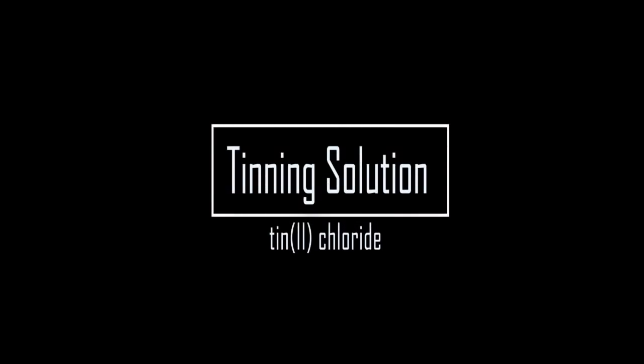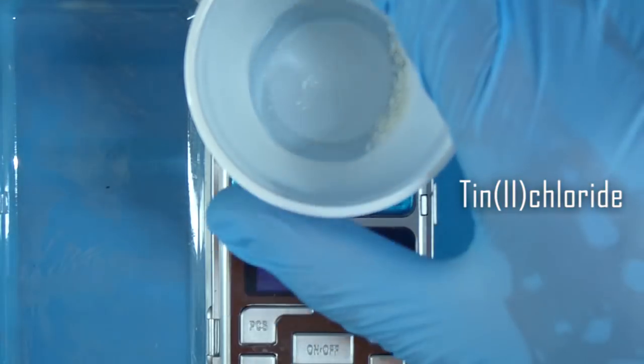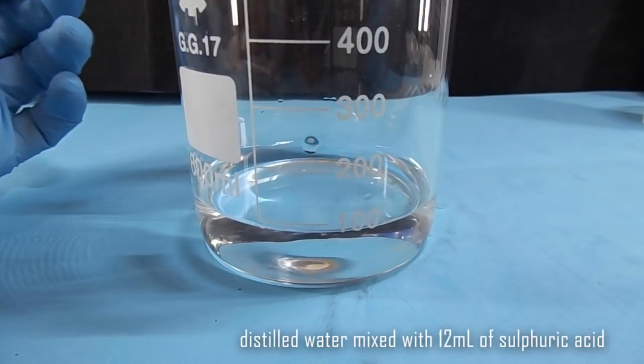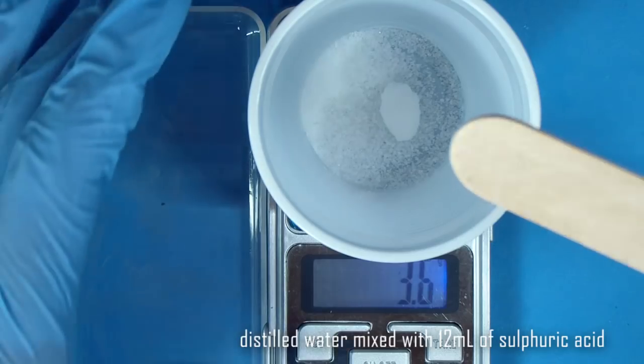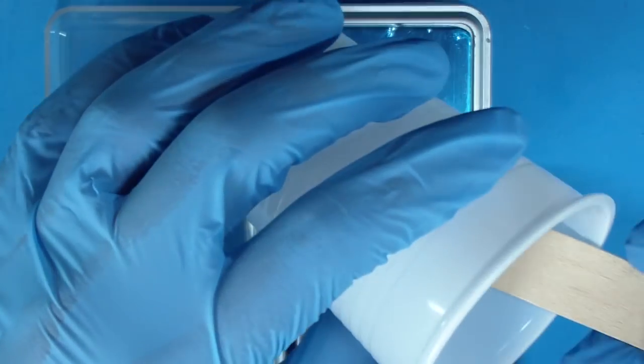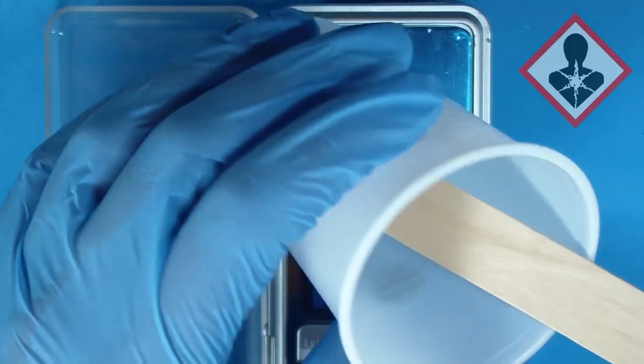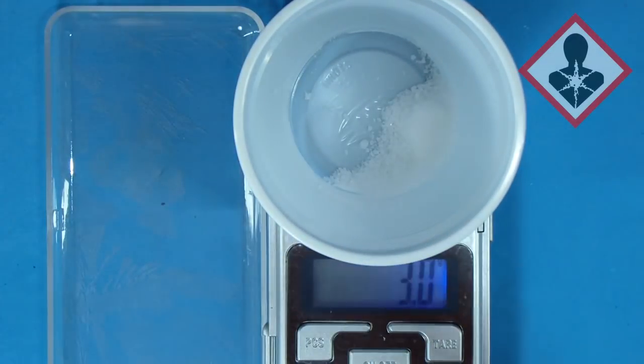Tin plating solution. To make tin plating solution we need to mix 0.4 grams of tin(II) chloride with 100 ml of distilled water, mix it with 12 ml of sulfuric acid, then add 4.5 grams of thiourea to the mixture. It's listed as carcinogen, so please don't touch it or try to rinse the thing. Take a look at description for materials data sheet.